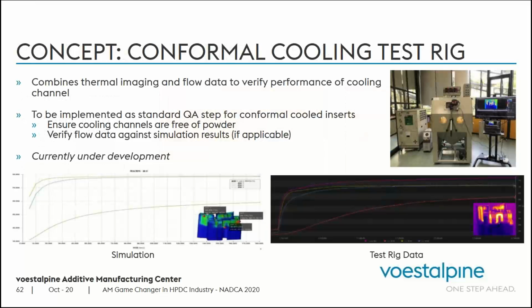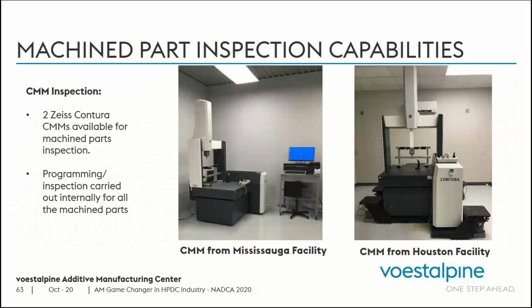And then when required, we do the conformal cooling test rig just to ensure cooling channels are free of powder and to verify the flow data against the simulation results as well. This we have a CMM